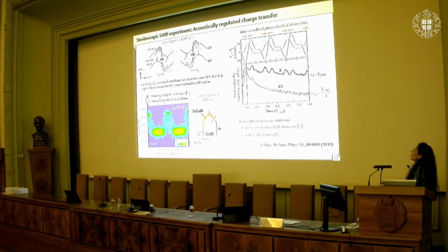So we basically increased the RF signal in order to get a stronger longitudinal field value, and also we deliberately now apply complex periodic waveforms, so not sinusoidal anymore, which we can track by the response of a nanowire quantum dot sensor. Now, you see here that these oscillations in the intensity are much more pronounced, and again, you see that they exactly follow the form of this longitudinal piezoelectric field component.